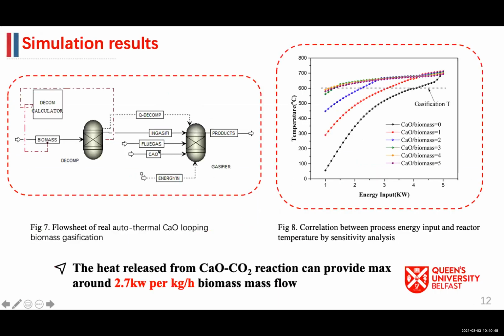So for the Aspen simulation, as you can see from this flow sheet, we used no heat duty mode for the gasifier, and all the materials input was set as room temperature. By modifying the energy input to the process, we've got a relationship between process energy input and reactor temperature by Aspen sensitivity analysis. As shown in this figure, the black line is the traditional biomass gasification.